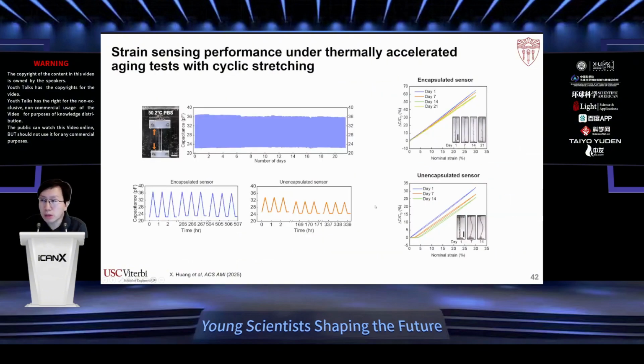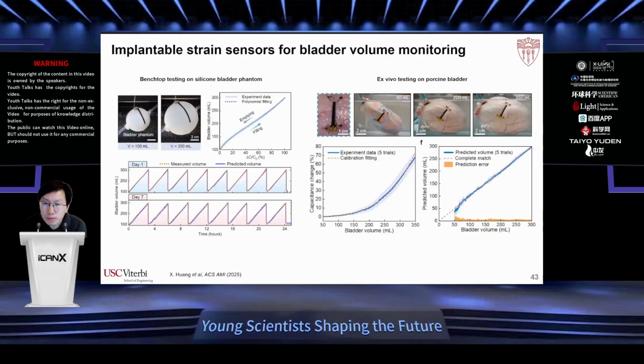And we demonstrate that this stretchable encapsulation is effective on our soft strain sensor immersed in PBS over 3 weeks. We show that with the encapsulation, we can significantly reduce the swelling of the soft substrate and reduce water penetration into the electrodes. And this is a simple demo. We show that this stretchable strain sensor may be attached to a bladder, and we can use the strain sensing data to predict the volume of a bladder in this ex vivo study.